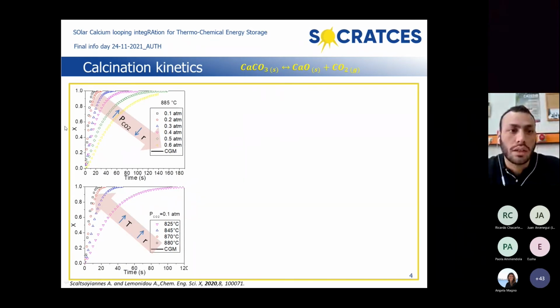Here you can see some conversion time curves for different CO2 partial pressures in the first figure and various temperatures in the second one. We can see that increasing the CO2 partial pressure, the rate decreases as the driving force of reaction also decreases, while increasing temperature leads to an increase in the rate for this endothermic decomposition reaction.